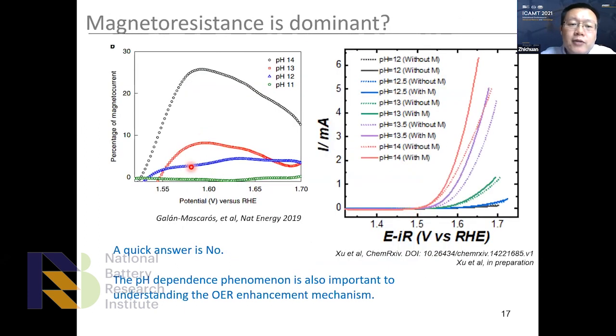So let's say the first question is whether a resistance change could affect the observed result. The quick answer is no. Magnetoresistance, that is, a resistance change of an electrode under the magnetic field, is very common for ferromagnetic materials. The direct answer is that this is not dominant, because we can observe the pH dependence, okay? If it were because of the resistance change of the electrode, we should not observe such a pH dependence. Instead, it would happen at all pH values, right? Even in acid, right?